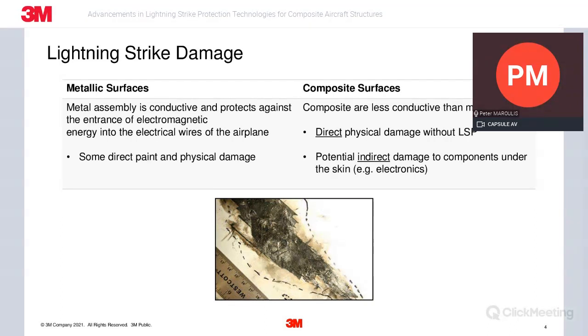Composite materials are chosen due to their light weight and more flexible nature, but they don't handle current like metal. As we have alluded to earlier, metal structures tend not to be as damaged as composite surfaces. Aluminum is highly conductive, and when struck by lightning, you'll typically see paint damage at the location of the strike. Depending on the intensity of the strike, we may see some pinhole burns within the aluminum to a decent-size large burnout area. But again, this is not common for metal structures.